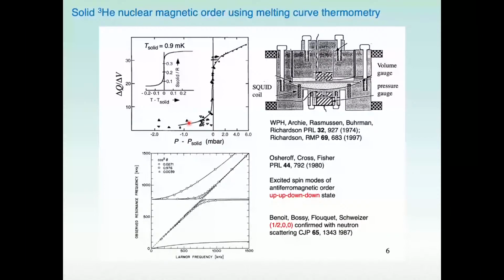But to complete this early discussion, the Pomeranchuk cell that achieved these results is shown here, where liquid helium-4 is used as an inert hydraulic fluid, and the displacement of capacitor plates measures the volume, and similarly, capacitor plates at the bottom measure the pressure. Now back to Doug Osheroff's measurements on single crystals that were created down here in the ordered antiferromagnetic state.